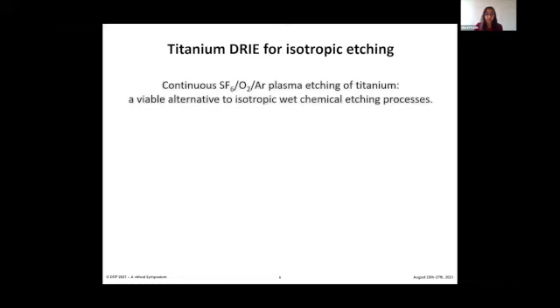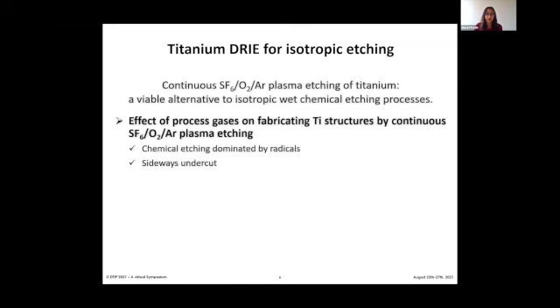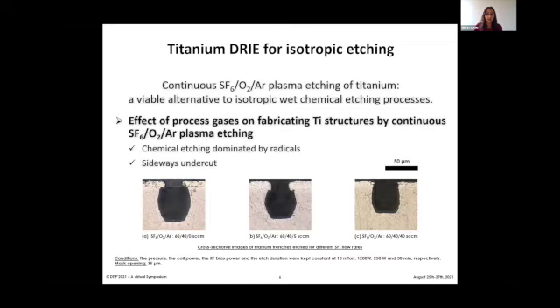A continuous SF6/O2/argon plasma process was investigated. The effects of the process gas flow rates on the geometrical features of the etched trenches, like the nickel hard mask etch rate, the etch depth, the sideways undercut, the profile angle, and the sidewall surface roughness were studied. The experimental results obtained after the etching suggested that tapered vias of varying profile angles can be formed by balancing the chemical-assisted isotropic etching, the passivation film by oxygen, and ion-assisted passivation etching.